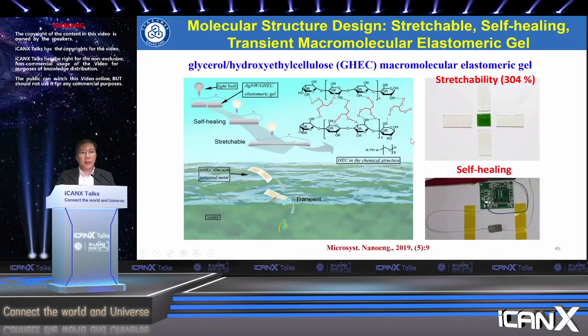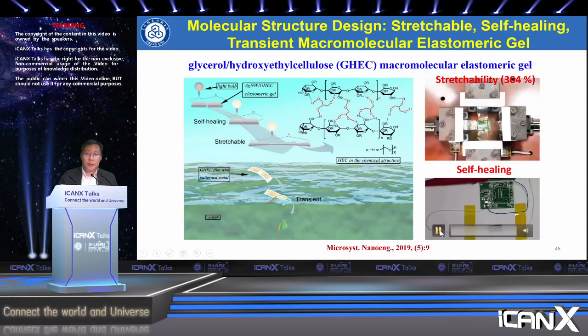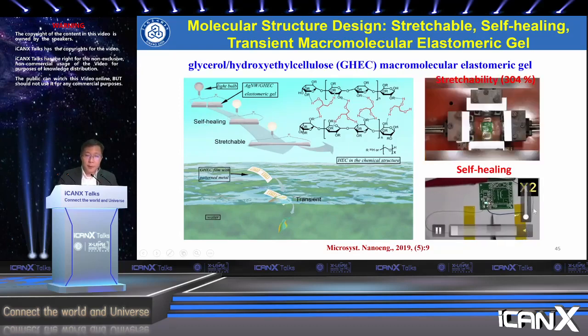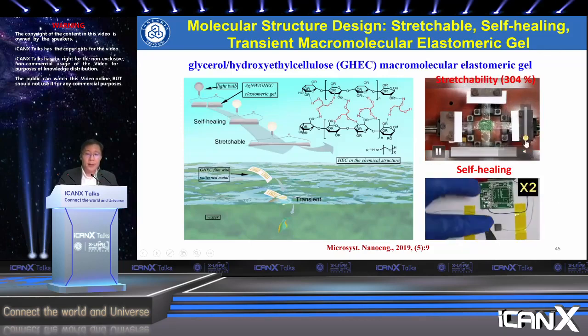Here I give you another example based on molecular structure design. We make stretchable, self-healing, and also transient macromolecular elastomer gels. We insert the small molecule glycerol into hydroxyethyl cellulose to form macromolecular elastomeric gels. So the dynamic hydrogen bond occurs between the HEC chains and the guest small glycerol molecules. So it gives you stretchability of about 300%, and also self-healing properties under ambient conditions.